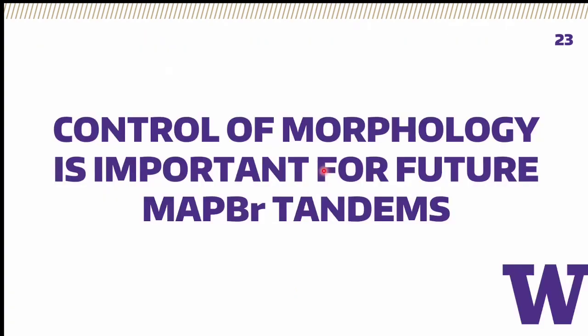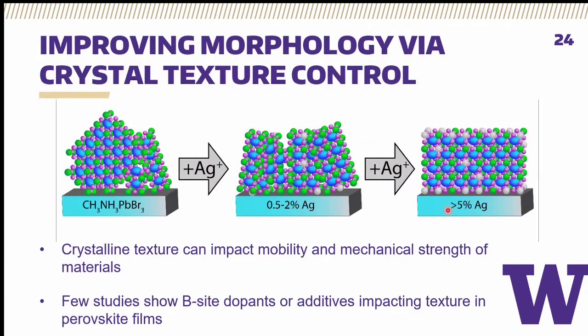But what we did learn from this is that control of morphology is important if MAPbBr3 is to be used in tandem solar cells, whether that be perovskite-perovskite or CdTe-perovskite tandems. And while micron scale morphology proved very difficult to tune in solution processed systems, we were able to improve morphology a bit using crystal texture control on the nanoscale by adding a bit of silver into our precursor solutions.